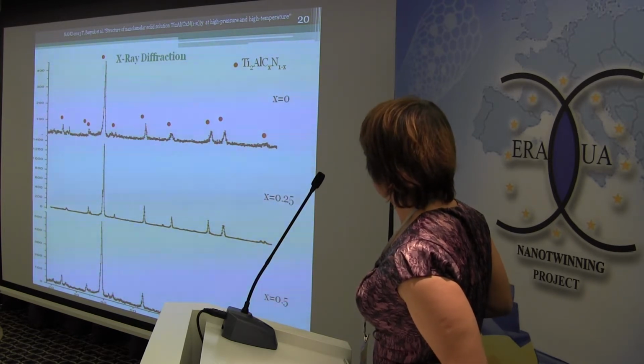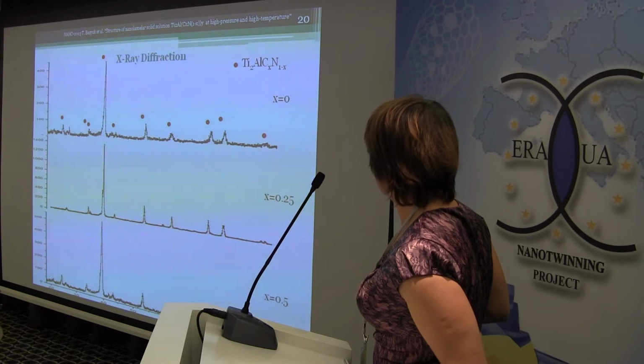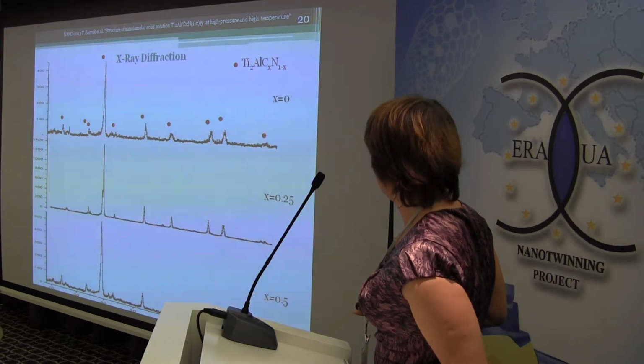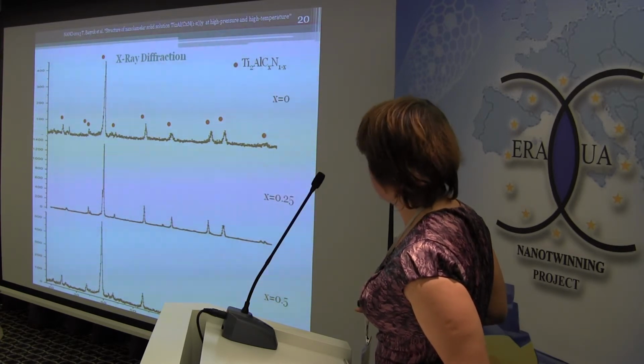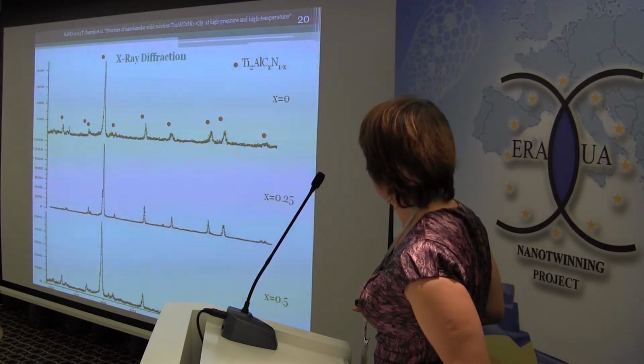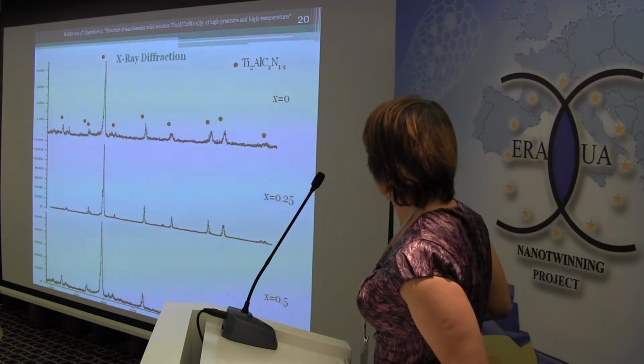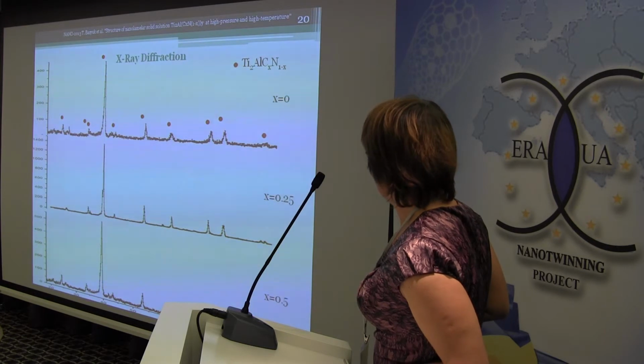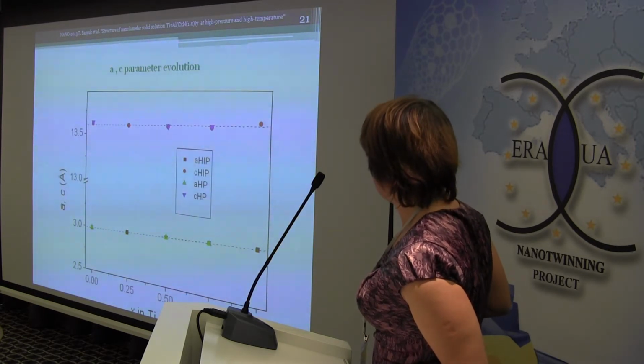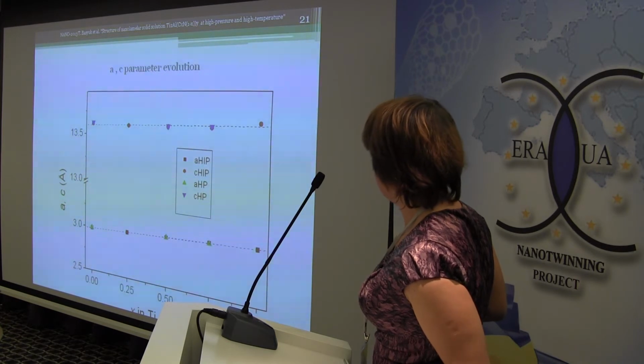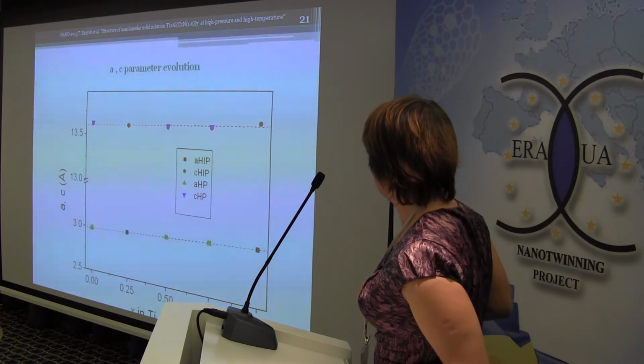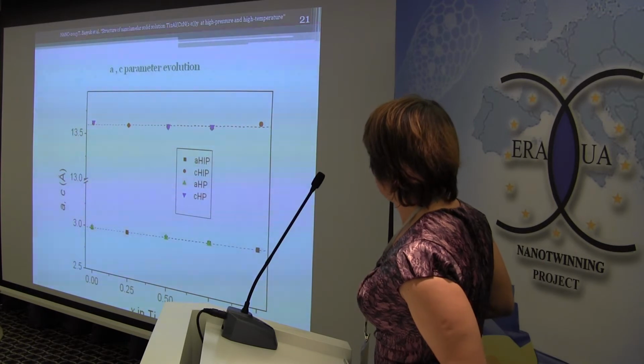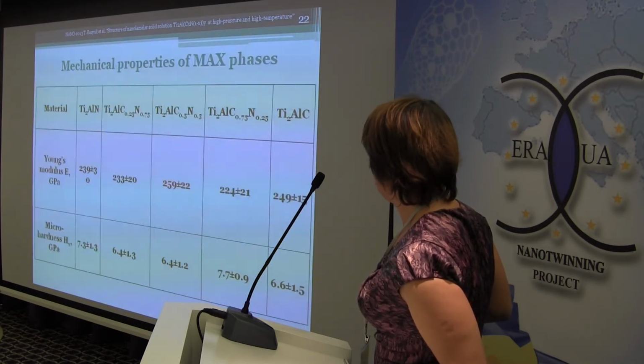From X-ray powder diffraction, we estimated that high pressure didn't destroy the MAX phases, and more than 92% of MAX phases were found in our samples. Some additional phases, such as titanium aluminide and titanium carbonitrides, were found, but no more than 5%. We estimated the A and C parameters, and you can see that they depend linearly on the carbon content.